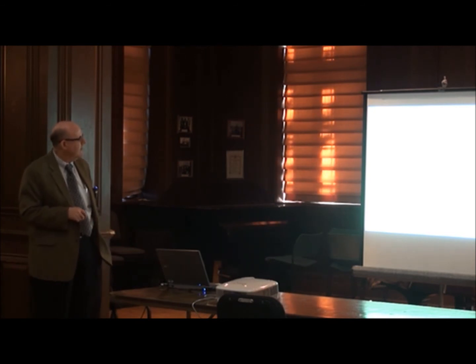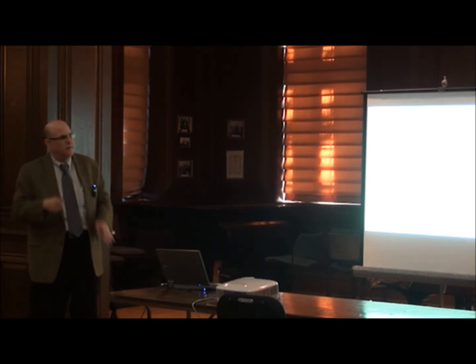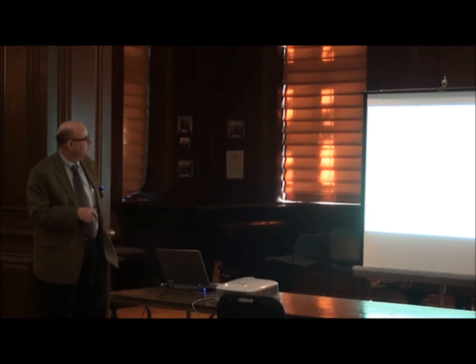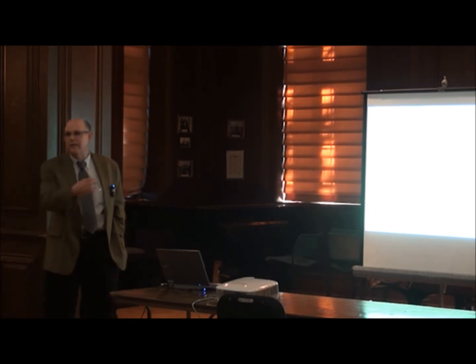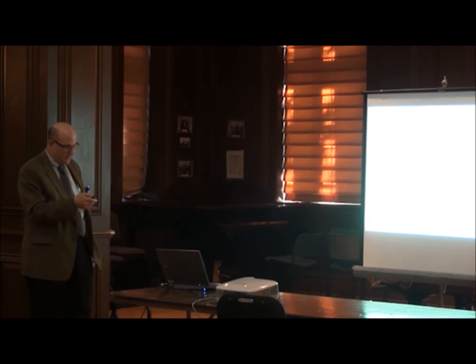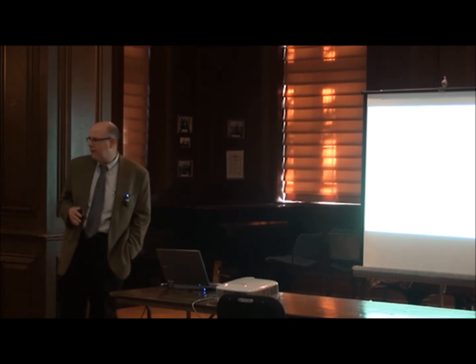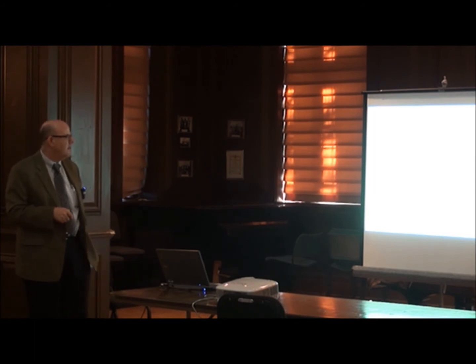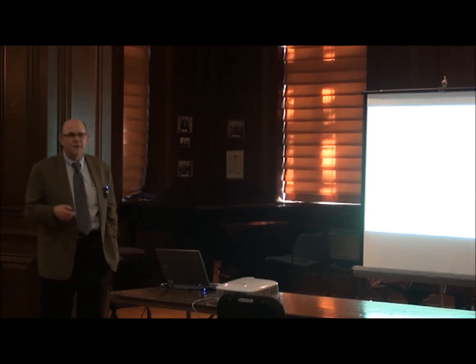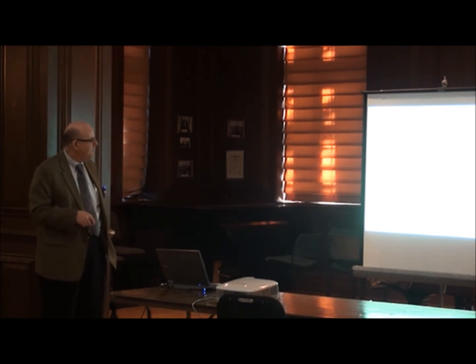In the case of longitudinal roughness, where the asperities are aligned in such a way that you have flow in the direction of motion, you get an augmentation of the flow. And if you have transverse roughness, you get a diminishment of the flow through that interface. And if you have some isotropic roughness, you have something in the middle. So as a result, we get this pressure flow factor that develops as a function of this lambda ratio, h over sigma.